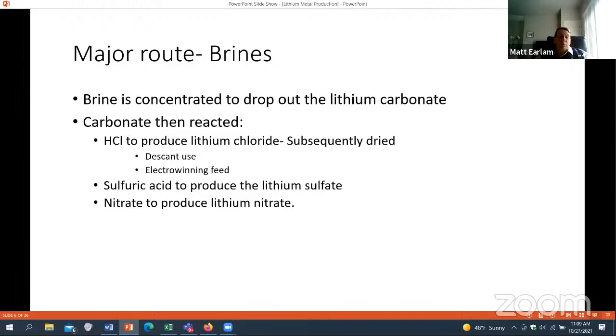If you want to produce lithium chloride, which is what we have to do to make lithium metal, then we obviously just react lithium carbonate with hydrochloric acid, and we produce a lithium chloride, which then we can, if we control the chemistry right, make a very strong brine, so we don't have to remove a lot of water in the evaporation process. You can add sulfuric acid to produce a lithium sulfate. Some people use lithium sulfate in chemical use. And then, of course, there's some lithium nitrates as well.